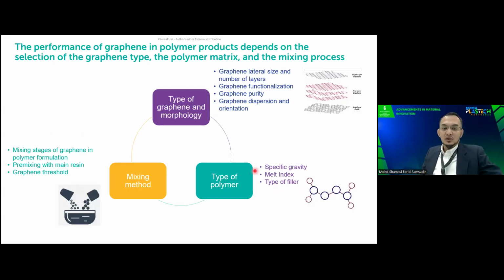Overall, the performance of the graphene in the polymer depends on how we select the graphene type in terms of morphology and lateral size, and whether we need to do functionalization treatment to improve the compatibility between the particle and the matrix. And in terms of the selection of polymer, we need to understand the MI of the polymer, whether the MI is sufficient to blend with this graphene particle, and whether we add in other types of filler, because then we also need to consider the size. If we choose the wrong size of graphene, it may not perform as we expected.